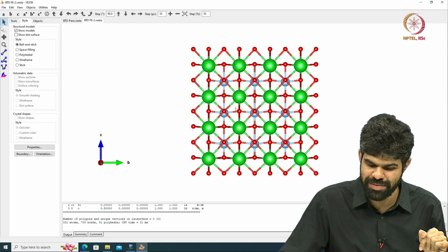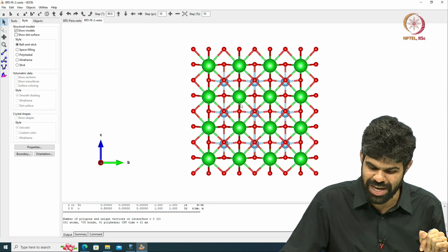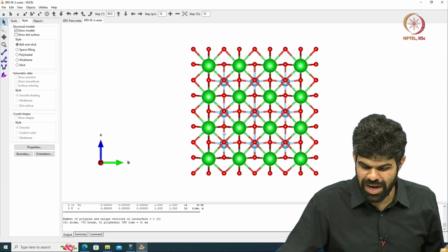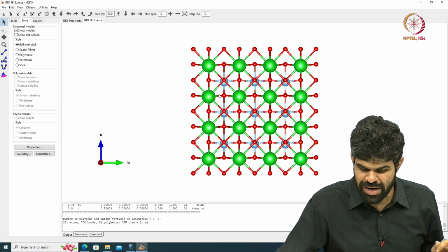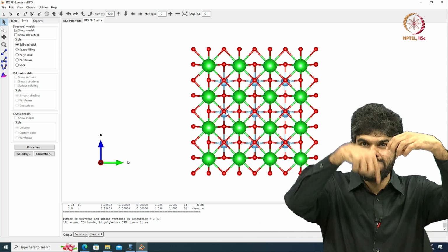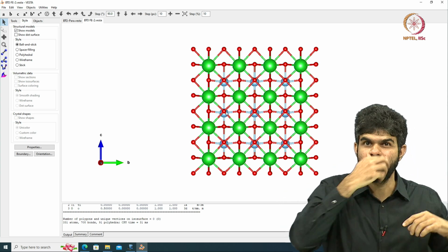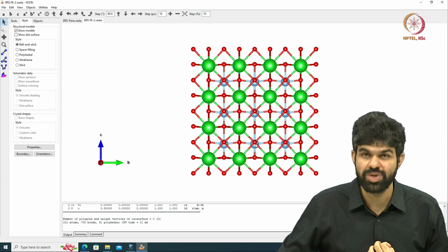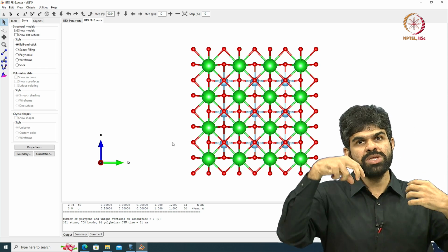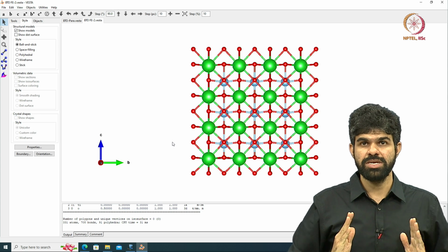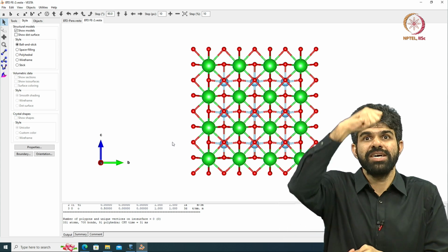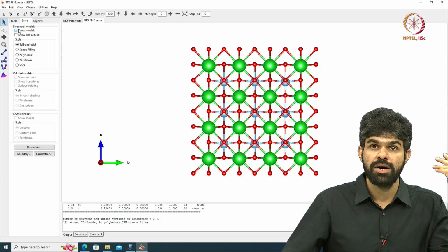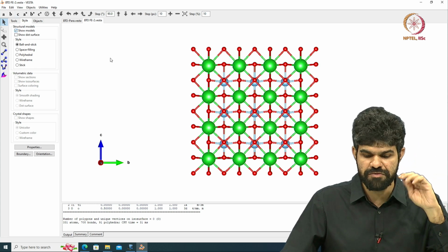I look at it along the A axis, titanium has moved down, right. So, in this case all titaniums are moving down, all the oxygens are sort of moving up, right. So, this oxygen and this oxygen have moved up. So, I have made a distorted octahedron of oxygen, and I have made titanium, where the polarization has titanium moved down, right. So, I did this sort of a thing with respect to this unit cell. Okay. Now, we know that titanium has moved down and the oxygen octahedra has distorted. So, the question is, can we actually find out the remnant polarization of this structure, right.